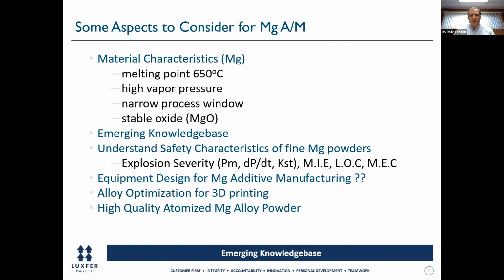So looking at some of the aspects to consider for magnesium additive, you're looking at material characteristics. Magnesium melts at 650. However, it has a high vapor pressure, which presents some challenges because you're really melting the magnesium powder in these processes. So you've got to be able to address how you're going to adjust the gas flow and account for the magnesium evaporation or the vaporization that's taking place. There is an emerging knowledge base, which is evidenced by the large body of data which is being published.